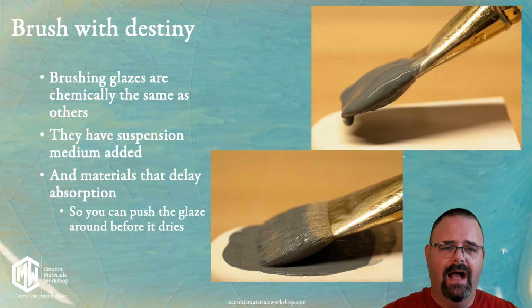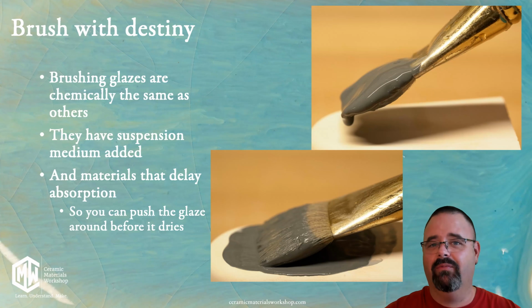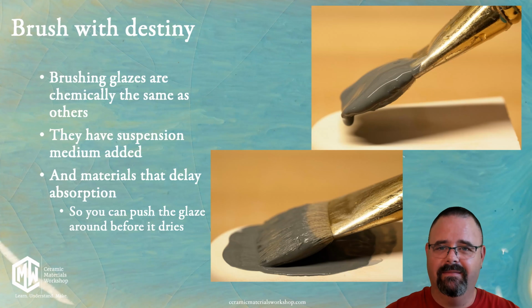And the other is the brushing medium, and this is intended on keeping the bisqueware from having capillary suction. Because if you've ever tried to brush on a dipping glaze, what happens is that the brush just dries up right away. The water gets sucked into the bisqueware, and then it becomes hard to push around. Most commercial glazes will add in a medium that keeps the water from being absorbed in the bisque very quickly so that you can push it around and try to level your application. But as I said, the actual formulas and chemistries aren't all that special.